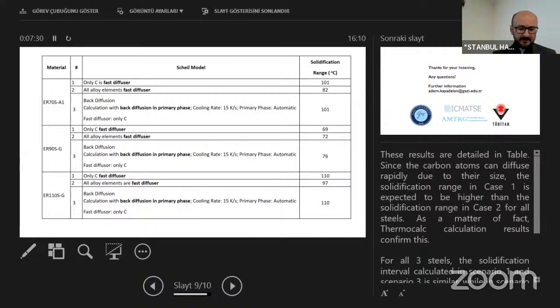For all three steels, the solidification interval calculated in scenario 1 and scenario 3 is similar. Scenario 1 is case 1, scenario 3 is case 3. While in scenario or case 2, the solidification interval is smaller than the other two scenarios. Only for ER90S-G, a small calculation error was observed in scenario 1. This was explained in detail above.